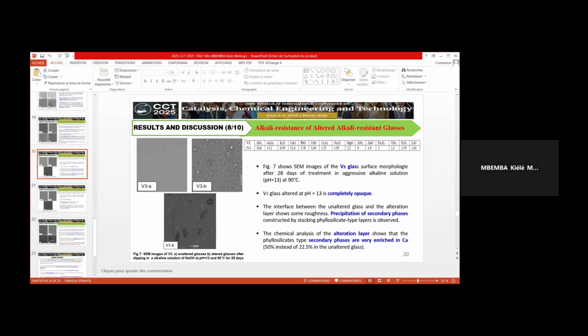Concerning the alteration of V3 glass, we can see that V3 glass is completely opaque. We can also note precipitation of secondary phases, and the chemical analysis of the alteration layer shows that phyllosilicate-type secondary phases are very enriched in calcium, 50% instead of 22.5% in the reference glass.